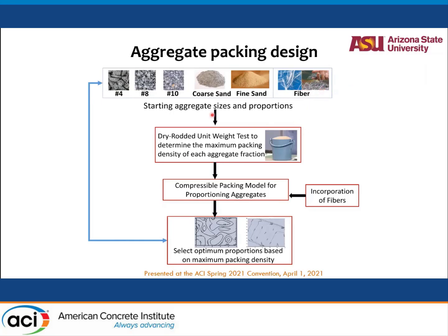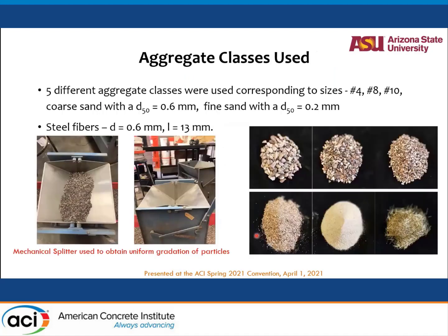So the way that we do packing is based on a compressible packing model, where you find the dry rodded unit weights of all of these components to find the maximum packing density of each fraction, and then use that in a compressible packing model, which again, we have made into very easy to use software to find the optimum proportions based on maximum packing density. So we had a number of different combinations. We used 5 different aggregate classes, 3 aggregates and 2 sands, coarse and fine sands. And we use steel fibers also in this, 1/2 inch long steel fibers. So aggregates were all cleaned and washed and made sure that they don't have any dirt or deleterious particles.